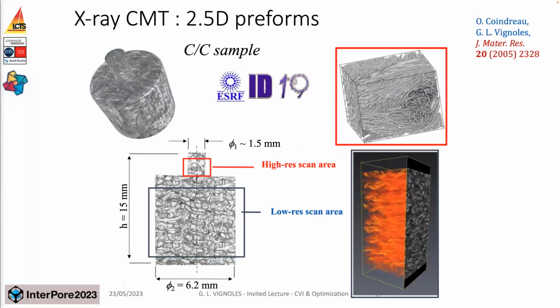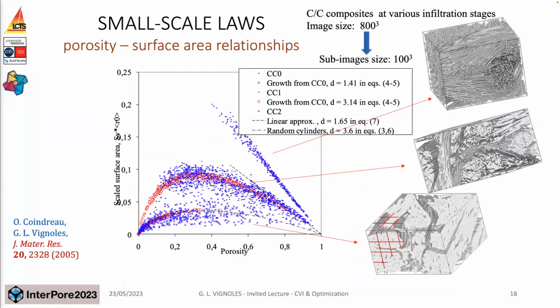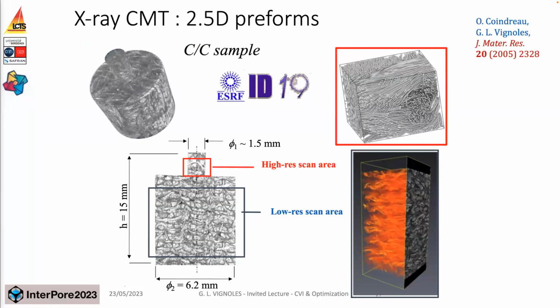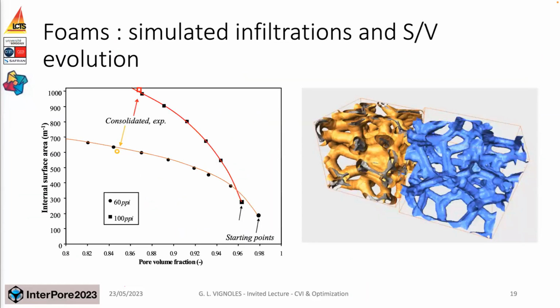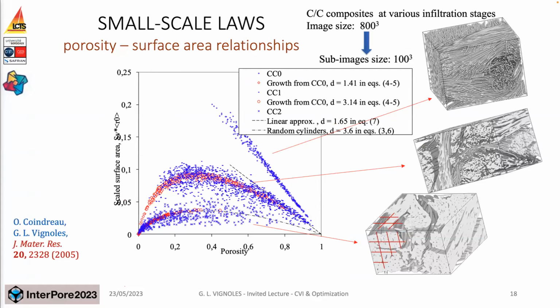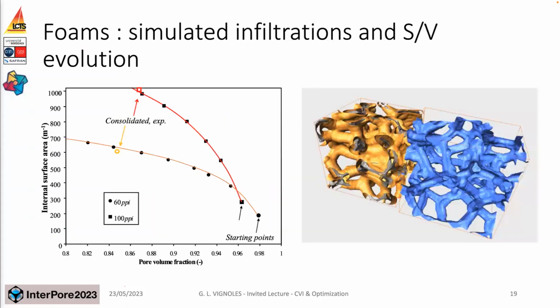Well, this is very old work now, but we've been going to tomograph many years ago and had low resolution and high resolution scans of these porous media. And from those images, we could extract lots of information. For example, the distribution of internal surface area as a function of porosity, elements that we could relate to fiber growth models and percolation models. And we could do the same, of course, for foams, which have been reinforced by CVI deposits here.